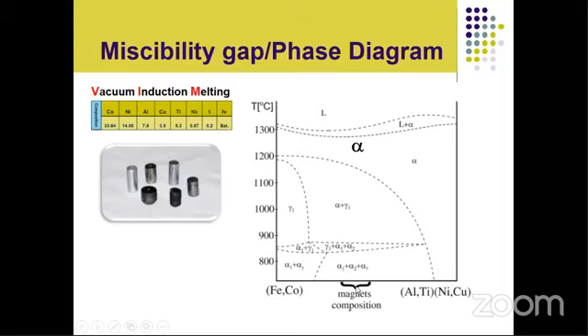When we mix all these materials and melt above 1400 degrees Celsius, the material is in the liquid form. When this material is cooled down, it undergoes different phase transformations, from liquid to alpha phase, pure alpha phase, from alpha to gamma phase, then alpha plus gamma phase, and then alpha prime phase. If we cool slowly to room temperature, we may come across various phases in the alloy, and some of these phases, like the gamma phase, are very harmful. So in order to avoid this, once we cast this alloy, the material is heated up to the single-phase alpha region and then quenched, either air quenched or oil quenched. During quenching, we can avoid the undesired phases like the gamma phase.